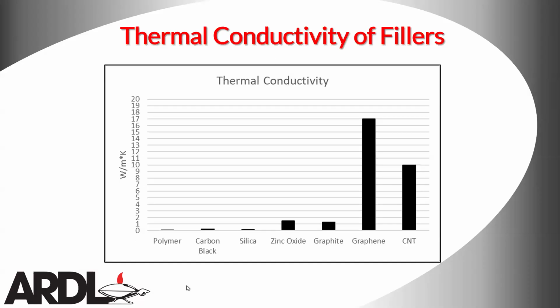and I was able to pull up some very basic ballpark thermal conductivity. If you look here, you can see polymer, as you would expect, has very low thermal conductivity, and this is because it does not conduct heat very well. Carbon black is a little bit higher, but not that much higher than the polymer. Silica is very similar to the carbon black. So traditionally, what goes into a tire tread compound is not very high thermal conductivity. Now let's look at the other fillers that we're going to look at in our study. Zinc oxide has quite a bit higher thermal conductivity than the carbon black or the silica. Graphite is fairly similar to the zinc oxide. And then you see the graphene is much higher, and so are the carbon nanotubes.